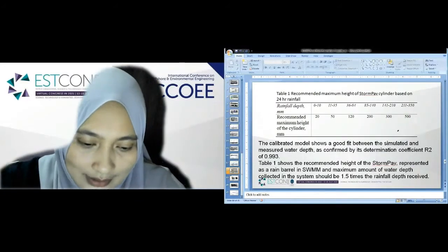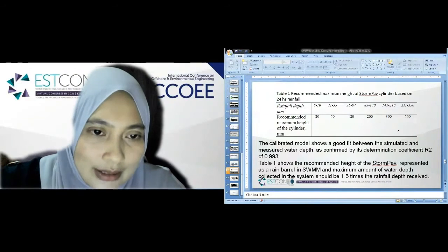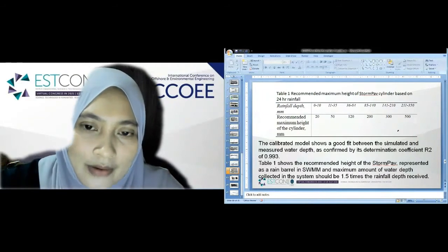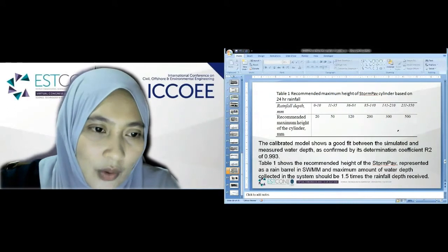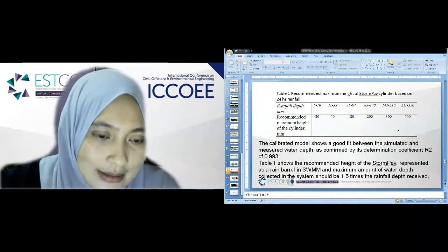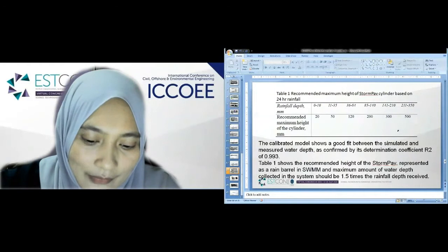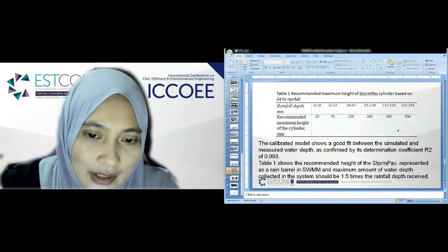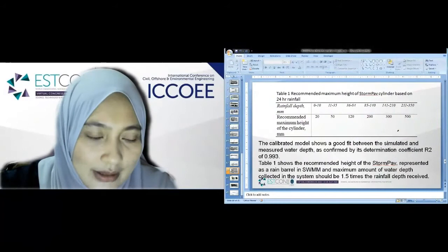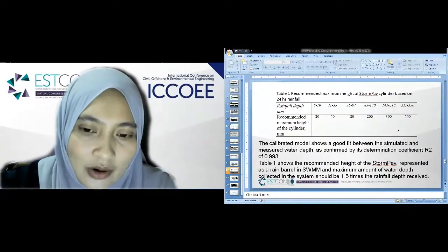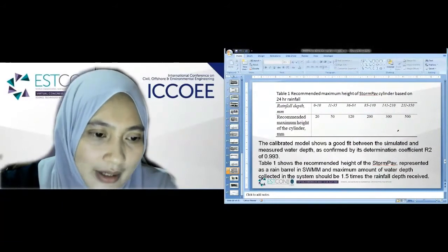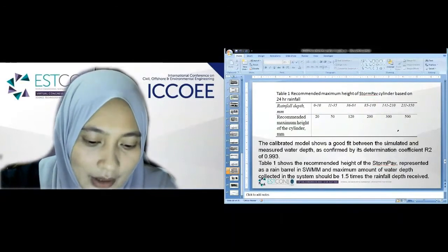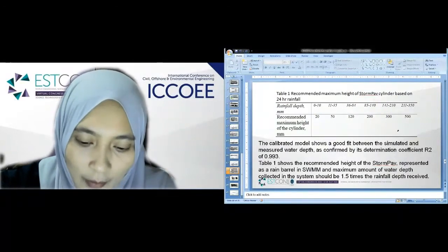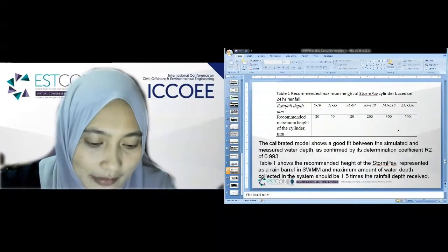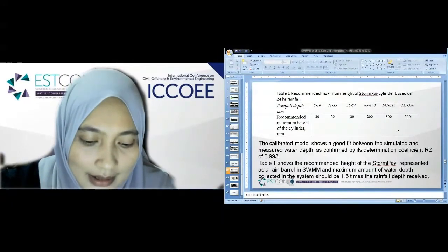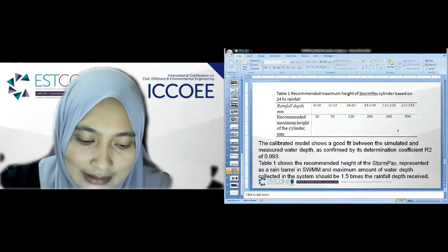Next is table 1. Table 1 shows the recommended maximum height of the StormPav cylinder based on 24-hour rainfall. When it is calibrated, figure 5.1 shows a good fit between the simulated and measured water depth, as confirmed by a determination coefficient R² of 0.993. Table 1 shows the recommended height of the StormPav, represented as a rain barrel in SWMM, and the maximum amount of water depth collected in the system.